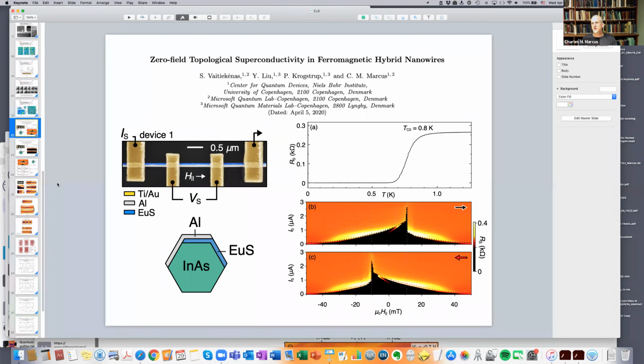If that's true, I believe it acts like spin flip scattering. And the spin flip scattering can reduce the gap and also drive it second order. See, we had a little bit of a problem. We saw a reduced gap. The gap was only a quarter the size of the zero field, or zero europium sulfide, gap. But if it was a first order transition, it's very hard to get something that's a quarter the size. Normally it just falls off the cliff.